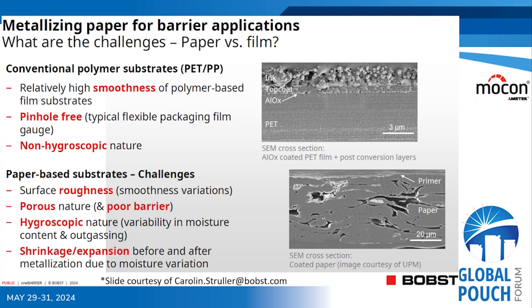The surface itself that you're trying to apply the coating to is rough. So you need to get your coatings to stick to it and be applied to it. And there's a lot of variability, a lot of variation. The substrate itself is porous in nature. I mean, we use paper as filters and the like. So when you have a very porous substrate, then you have to fill those pores with your coating, and really make sure that it fills very well, blocks everything through to get the barrier that you want.